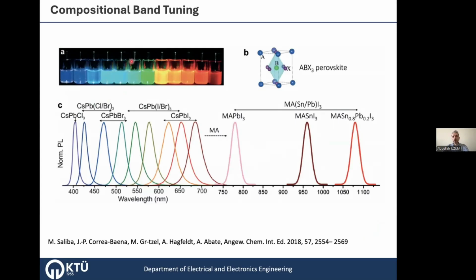Here are colloidal nanoparticles of perovskite under UV illumination. You see that they have different colors, and with PL, they show different peaks. That means different band gaps. With changing the halides, changing the metals or cations, you can change the band gap. And by mixing the halides, cations, or metals, you can even have intermediate band gaps between them. For example, from 1.77 to 3.06 electron volts, you can have different band gaps.